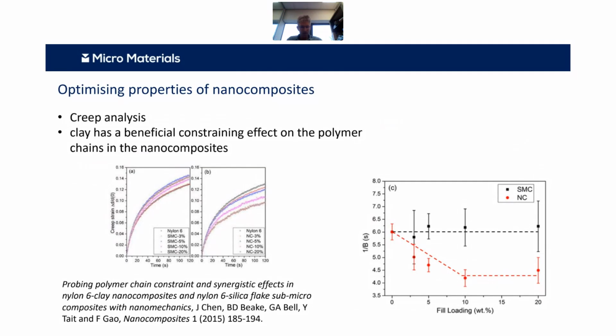And what you can see is that the time constant for the submicron composite essentially is not being affected by the filler loading, whereas on the nanocomposite it is significantly altered. So this is telling you again that there's a beneficial constraining influence on polymer chain constraint in one system but not the other.